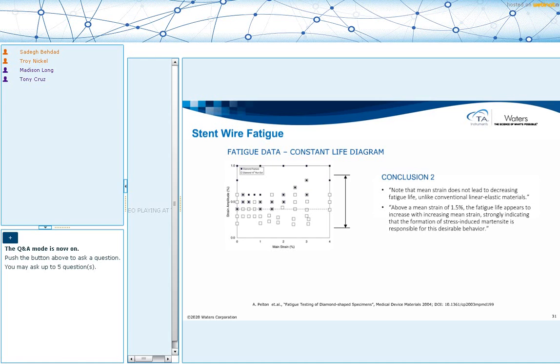And your x-axis is your mean strain, and your y-axis is the oscillation strain that was exerted on the sample on top of that. So at each point, you have to add your x and y coordinates together to understand how much total strain was applied to that sample. So the dashed line shows you the endurance limit that we found before, 0.1% oscillation strain. What is interesting here is that as we go from left to right, meaning that we are increasing the initial pull, the mean strain that we applied to that surrogate, we see that a higher number of samples survive.